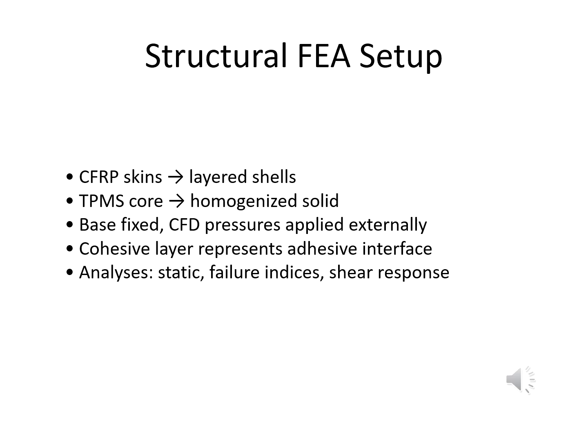The structural analysis is performed in ANSYS Workbench, using a combination of a layered shell element for the composite skin and solid elements for the homogenized TPMS core. A cohesive interface is inserted between the skin and the core to capture interfacial shear transfer and potential delamination, an important failure mode in sandwich structures.